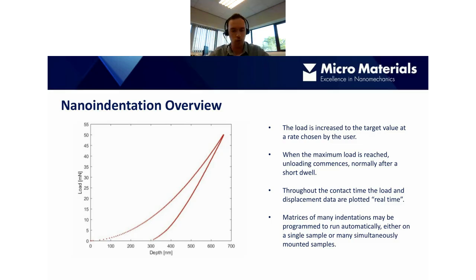So essentially, most nanoindenters have some sort of surface find procedure where they detect the surface, or the zero depth point of the sample, and then the load is increased to a target value at a rate, or a displacement rate, or a loading rate determined by the user. In this particular example, it's loaded up to 50 millinewtons.